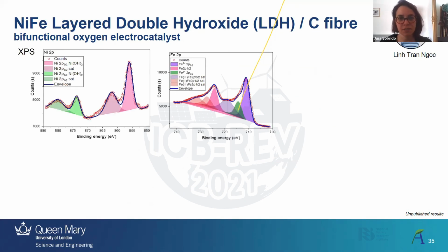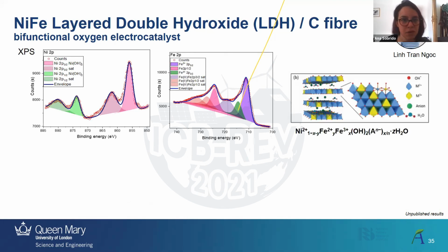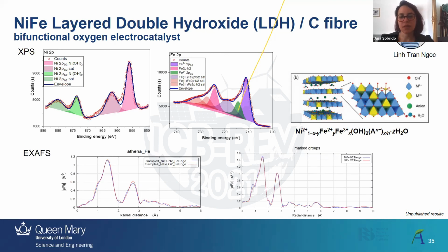So we did different tests. I'm going to show you XPS. I mentioned it's got some iron 2, so we find some iron 2 as well, so it's not surprising. And then we did some XRD at Diamond synchrotron to try to understand what the difference was. It doesn't seem to be something in the bulk, because both the one prepared under nitrogen and the one prepared under air seem to have the same XRD spectra. So that was also surprising. We were hoping to see some sort of differences in structure that way, but we couldn't.